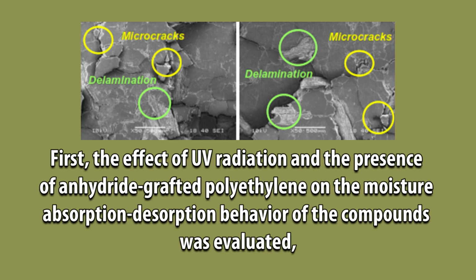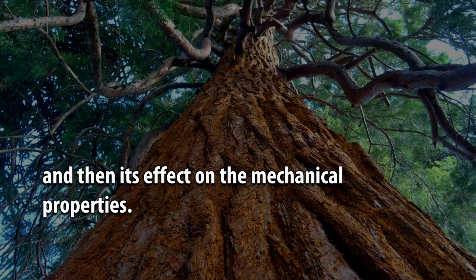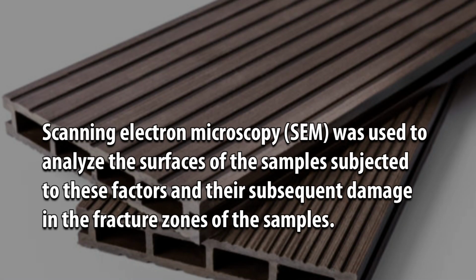First, the effect of UV radiation and the presence of anhydride grafted polyethylene on the moisture absorption-desorption behavior of the compounds was evaluated, and then its effect on the mechanical properties. Scanning electron microscopy (SEM) was used to analyze the surfaces of the samples subjected to these factors and their subsequent damage in the fracture zones of the samples.